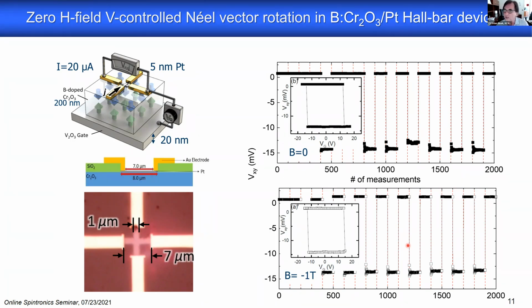He said, I don't see any change when I change the magnetic field. So I got angry and said, well, you don't see a change? Then why don't you switch off the magnetic field? Then you will. And he did that, and indeed, we still saw the exact same switching, no effect whatsoever. So what happens here is you apply one voltage, no magnetic field whatsoever. You apply a voltage, you switch from one state into the other state. You remove that voltage, the system stays in this state. You measure 100 times or how often you want. Then you switch the voltage of the other polarity. You switch back. You can take measurements and so forth.